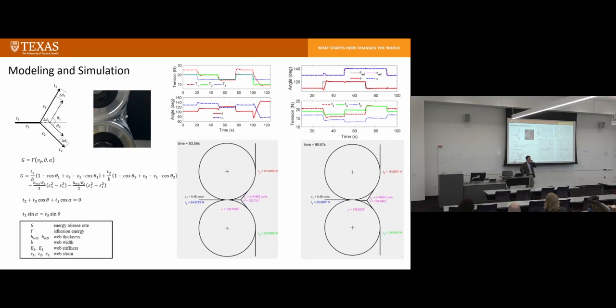For the peeling process, the peeling angle, as you can see later on, is very important for quality too. If you want a certain angle, can we set the tensions to control the peeling angle? So this is our process control idea. We want to set the angle. This is a simulation result. If you want to achieve different peeling angles, can we calculate the tensions needed to give us that desired peeling angle? The answer is yes, but there are some disturbances. The angle tracking is not that great, but you have to control your system to make sure it satisfies the result.